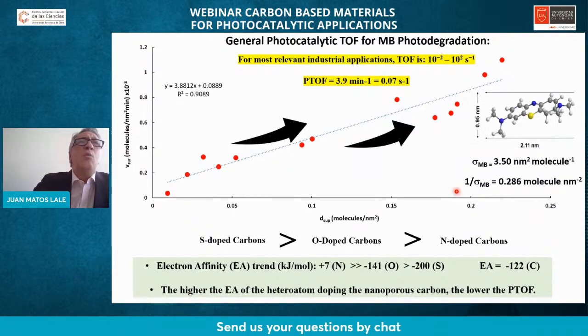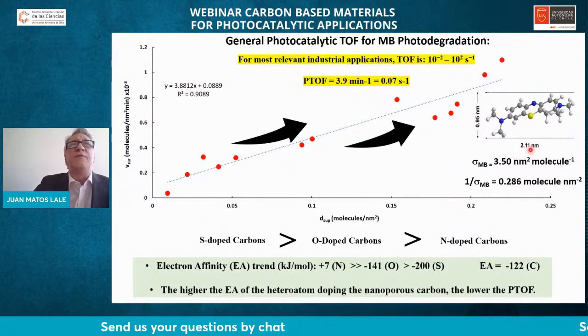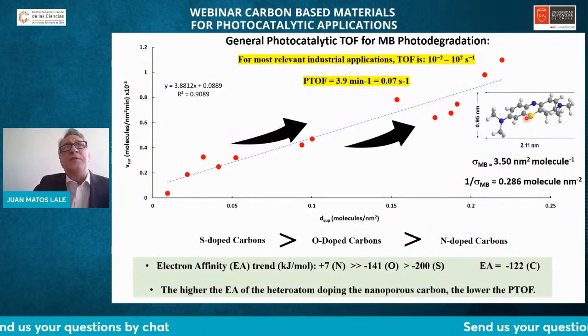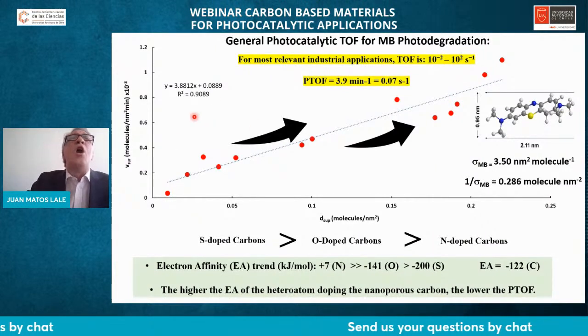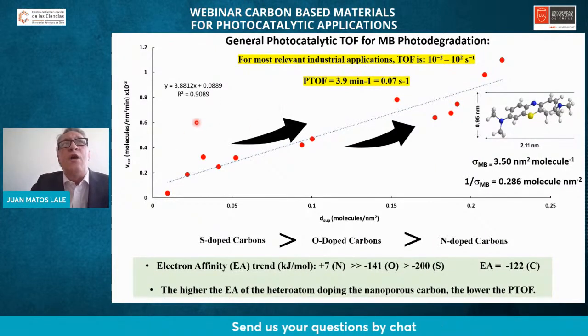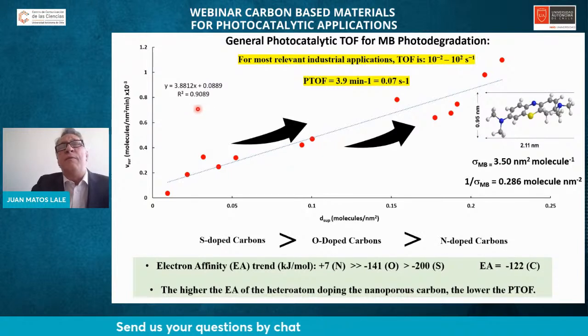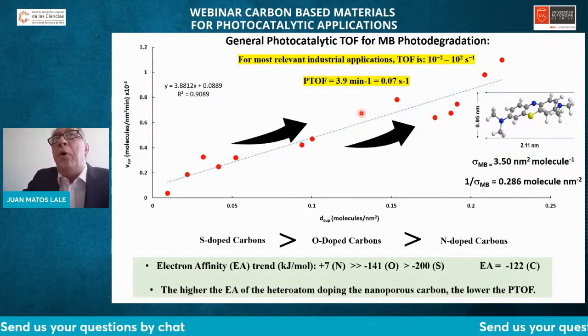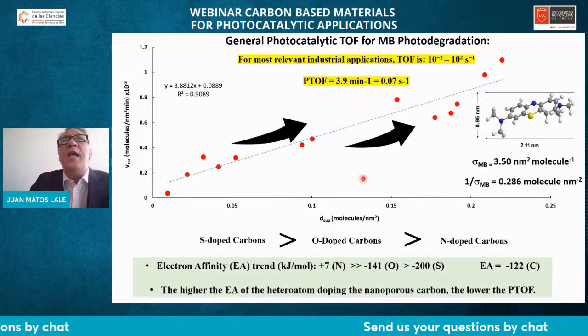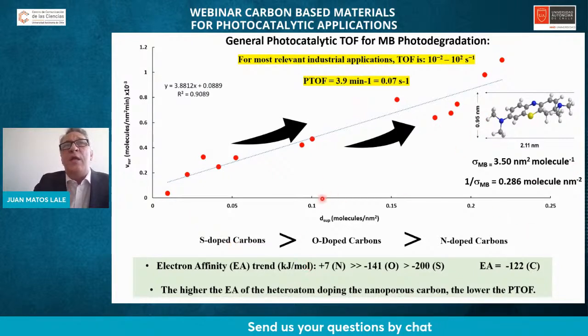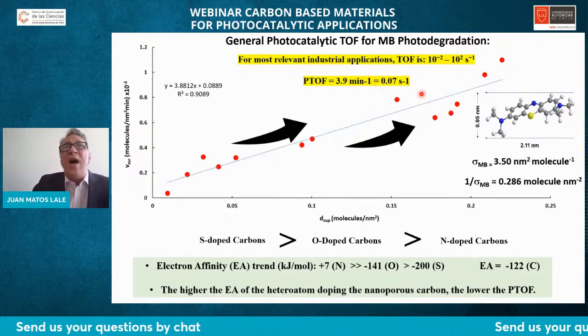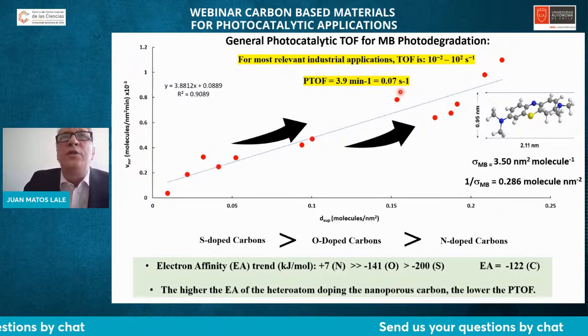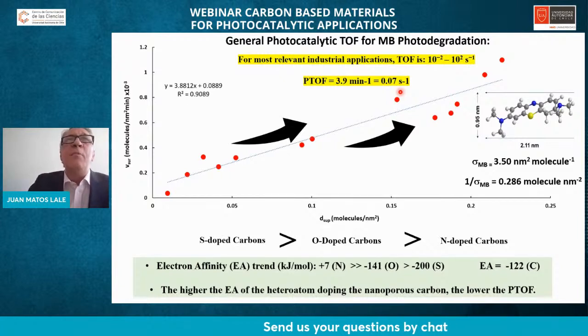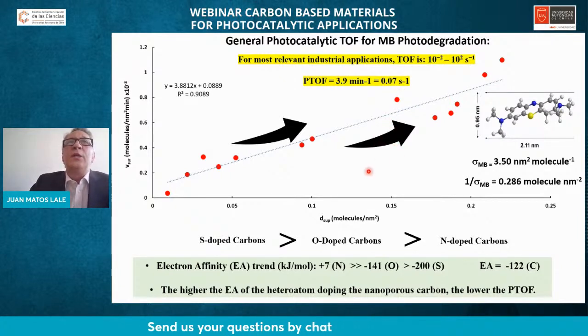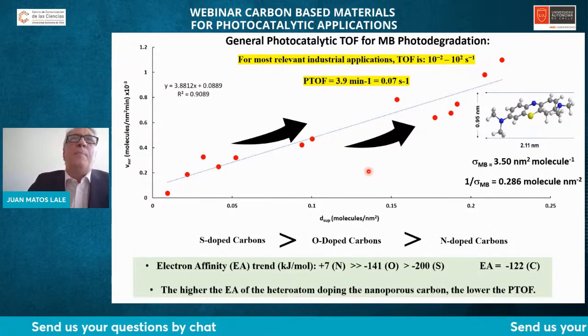In summary, when we put all the data together for the case of methylene blue, we achieve a very interesting relationship with a good enough, it could be better, of course, but good enough quadratic linear factor of regression. But the important thing is the P-TOF for the case of methylene blue. By using different kinds of heteroatom doped carbon-based materials, we have values in the range of the industrial application. It demonstrates that this technology can be scaled up.